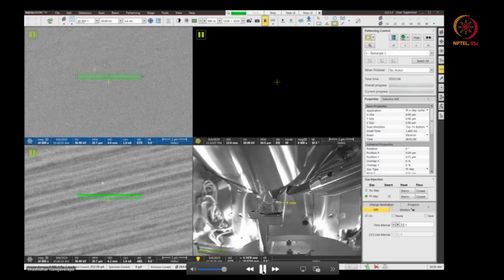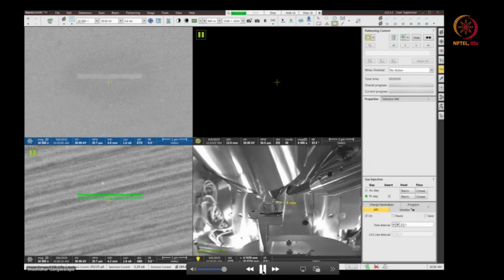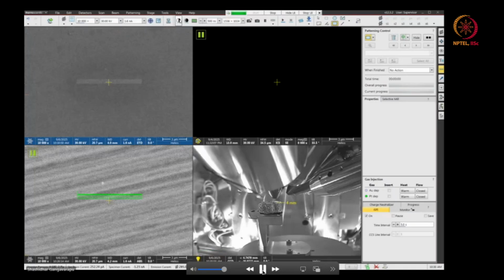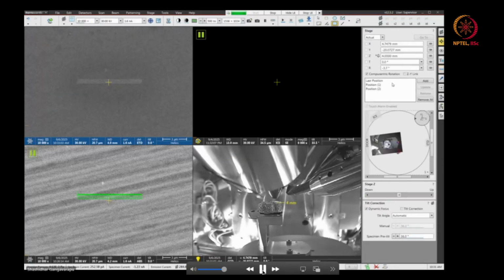Now you can see the platinum is nicely deposited on our sample surface, and in the E-beam window, in the secondary electron micrograph, the same rectangle pattern we put is the same platinum deposited on the surface.